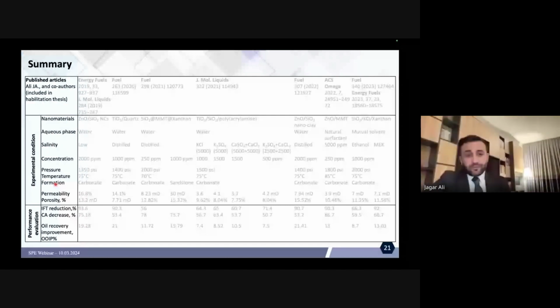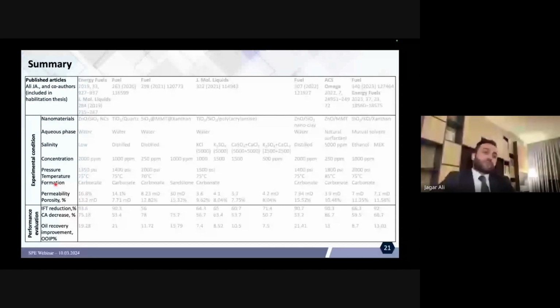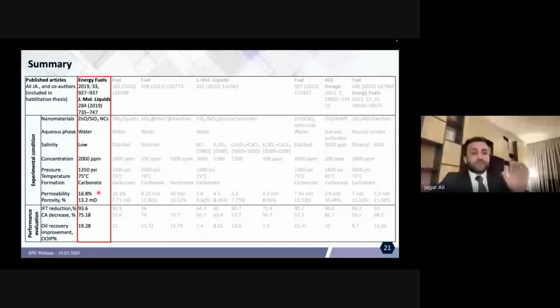The summary of the work is presented here. We have different publications as shown here for different nanocomposites with different conditions of the experiment. So from this row, it is about experimental conditions: the type of the nanomaterial, aqueous phase used, the salinity level, concentration, pressure, temperature, the formation type, permeability and porosity, and the performance evaluation, which is focusing on IFT reduction in percentage, contact angle decrease in percentage, and oil recovery improvement in percentage as well.